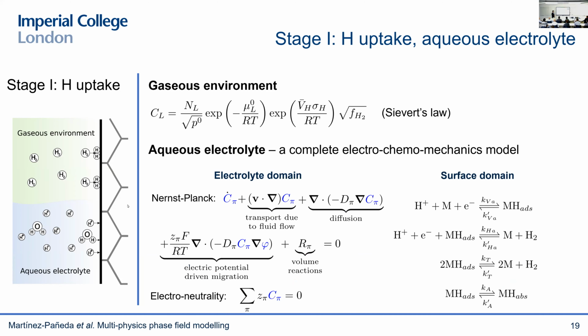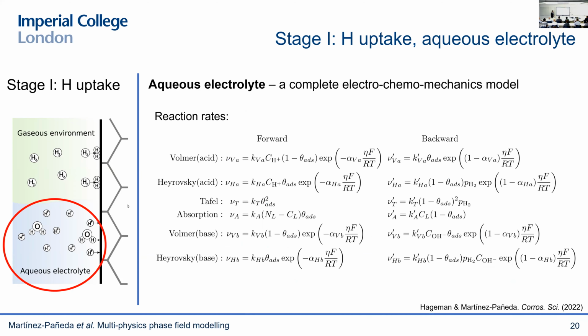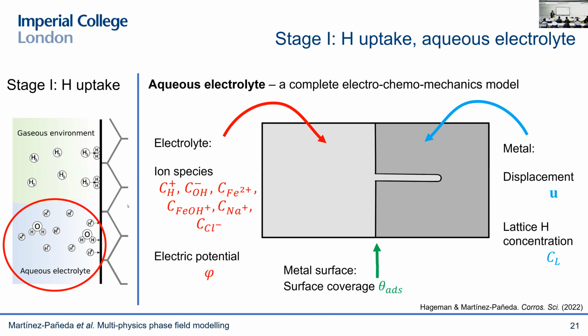So basically, this means that on the surface, you need to solve the hydrogen evolution reactions, so the Volmer-Heyrovsky-Tafel and absorption reactions. And in the electrolyte, you're solving the Nernst-Planck equations to be able to predict the concentration of ionic species and also changes in overpotential. And then, well, I'm not going to get into the details. You need to formulate all the reaction rates, but all these things depend on parameters that we can measure. They're all physical parameters. And then this is how your finite element model looks.